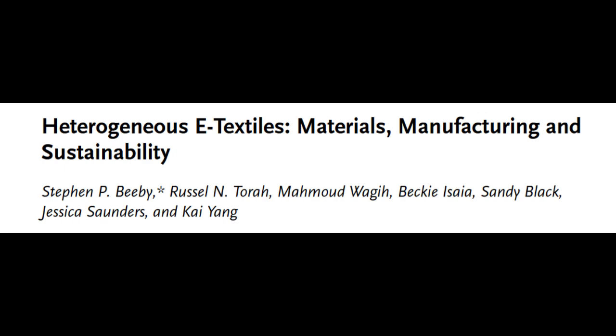Okay, so for covering large areas of fabric with these functional materials, what methods are typically used? Dip coating and spray coating are common for applying materials across the full width of a fabric roll, for continuous processing. Just dunking it or spraying it? Essentially, yeah. Dip coating has been shown to work at pretty high speeds, like 150 meters per minute, for applying graphene coatings in one example. Spray coating is also versatile, used for things like dielectric layers or even applying the different layers needed for solar cells. Solar cells printed directly onto fabric. People are working on it.